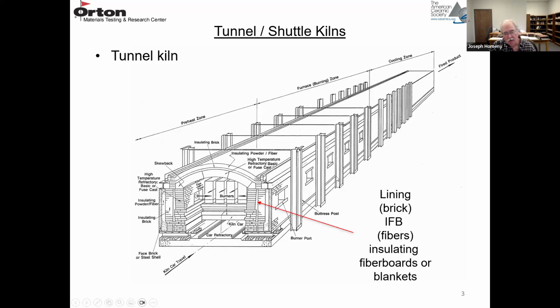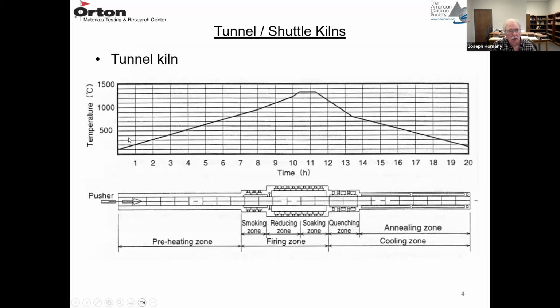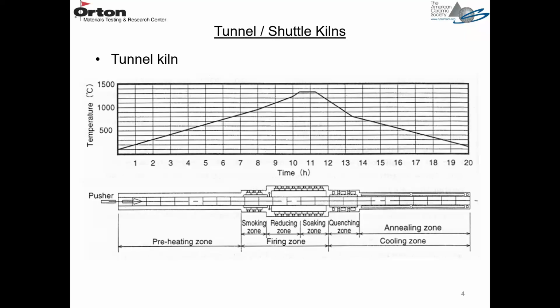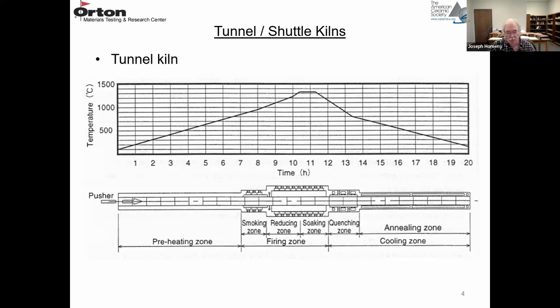So these are usually gas fired. You can see the ports on the side of this furnace, and they're adjusted to create this type of temperature profile. So there's the preheating zone, the sintering zone, and then the cool down or annealing zone. So in this firing zone, you can adjust the gas burners to be reducing or oxidizing. If you adjust the gas to air ratio, excess gas would be reducing, excess oxygen is oxidizing. So you could create oxidizing or reducing conditions.